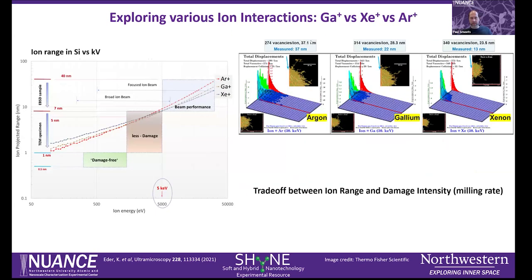So I've shown you some comparison of xenon versus gallium. Let's throw another ion in the mix - argon. On the left-hand side here is a plot of the ion range of these species in silicon versus the accelerating voltage. Here we have a 30 kV beam of argon. You can see that it penetrates deeper into the sample versus xenon, which actually penetrates at more shallow depths.